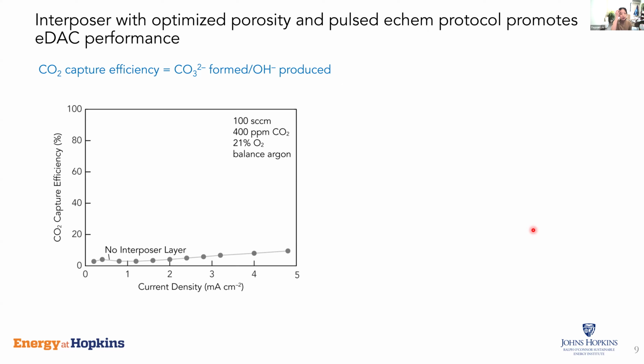So with this interposer layer, we went ahead and tested the carbon capture performance using 400 ppm CO2 plus 21% of oxygen mimicking the air condition. So without the interposer layer, which is only the oxygen reduction catalyst along with the membrane, you can see the capture efficiency is really low. So the capture efficiency here is defined as how much carbonate is being formed versus how many hydroxides being produced using our electrons, right? 100% carbon capture efficiency means that all the hydroxide electrochemically produced are reacted with CO2, which is what we want.